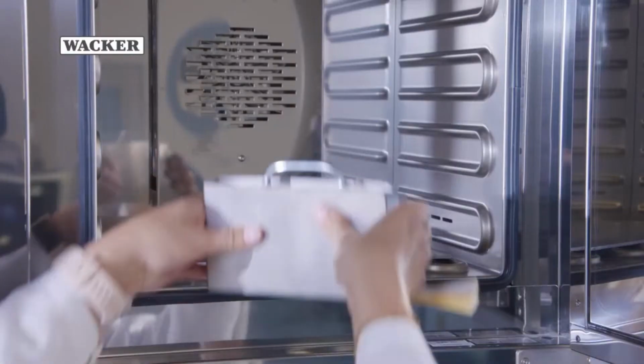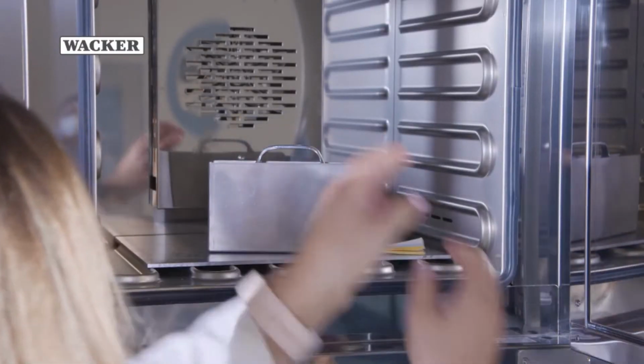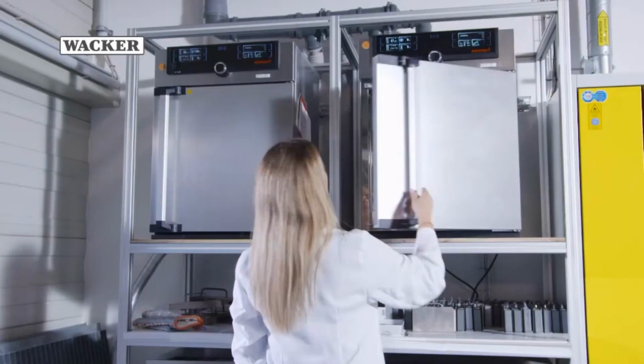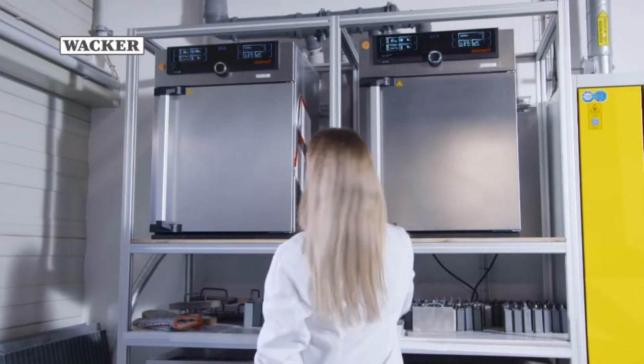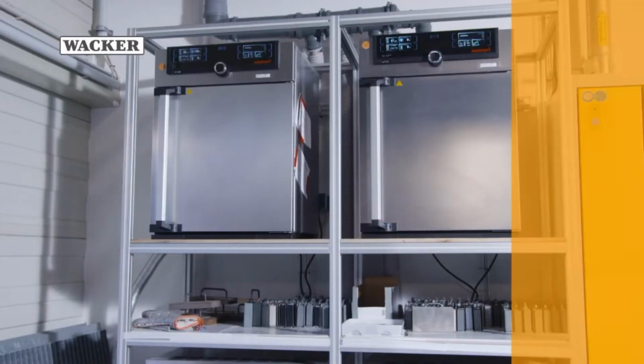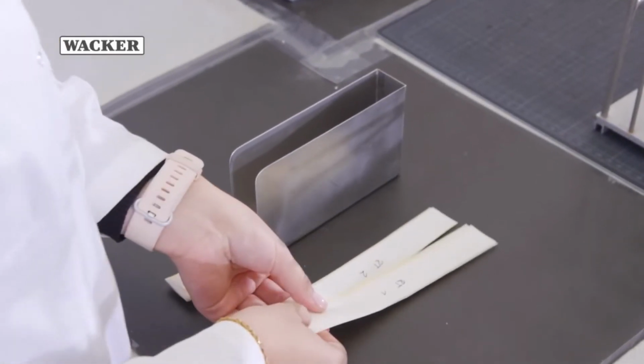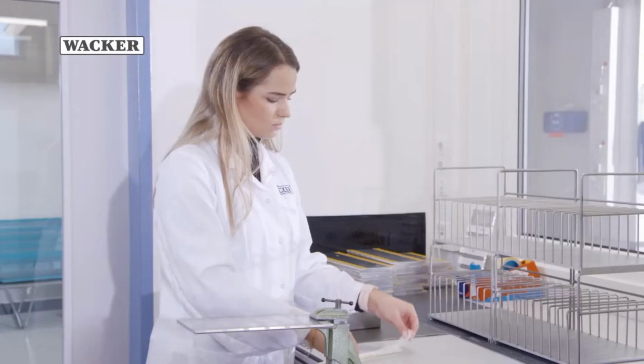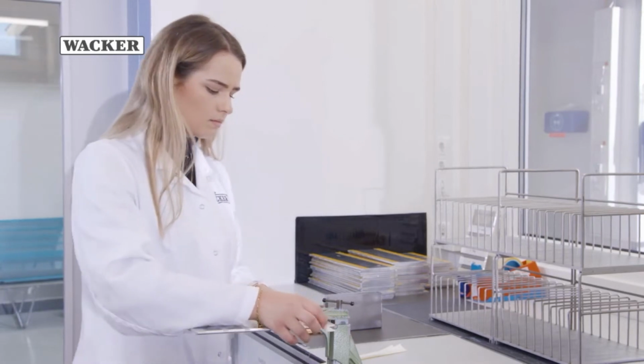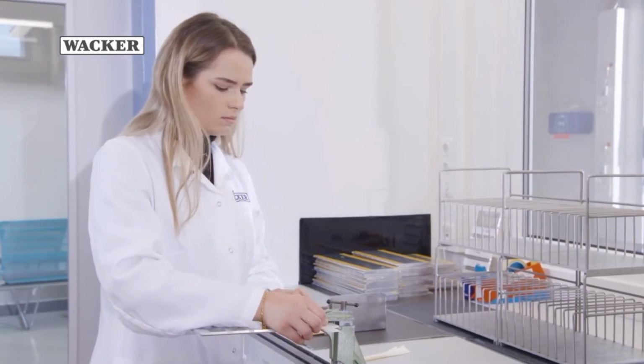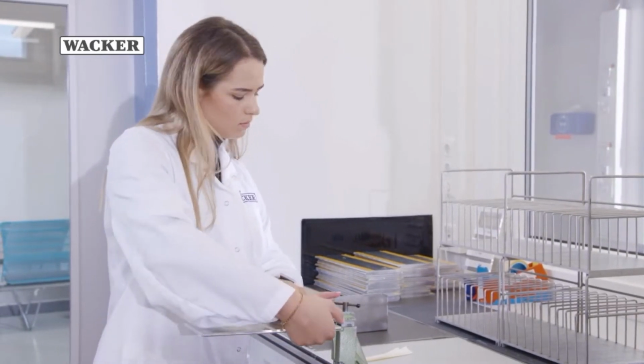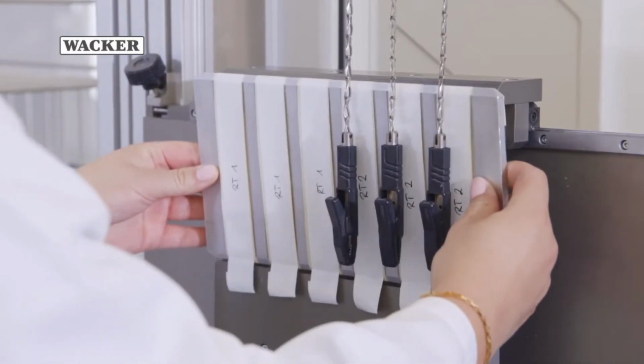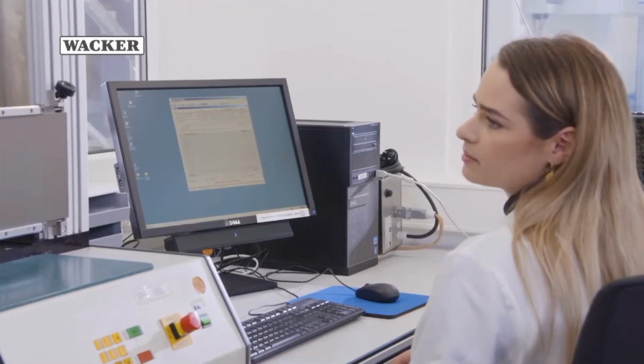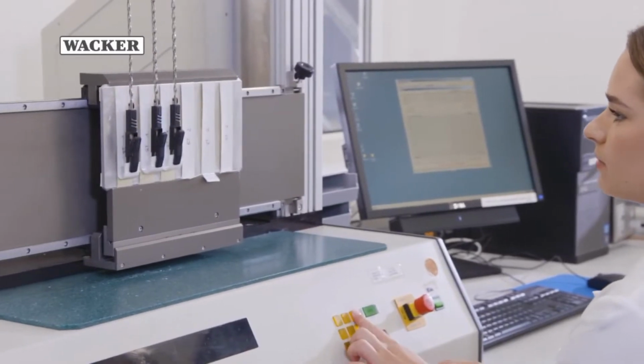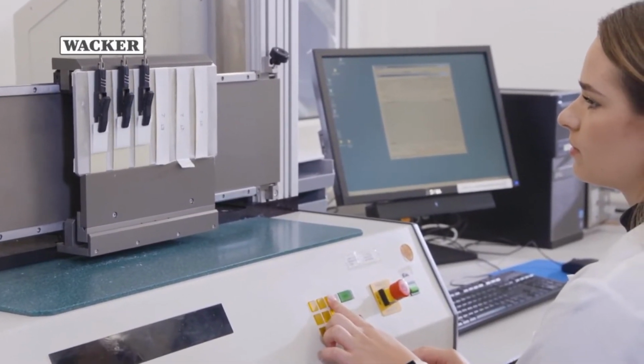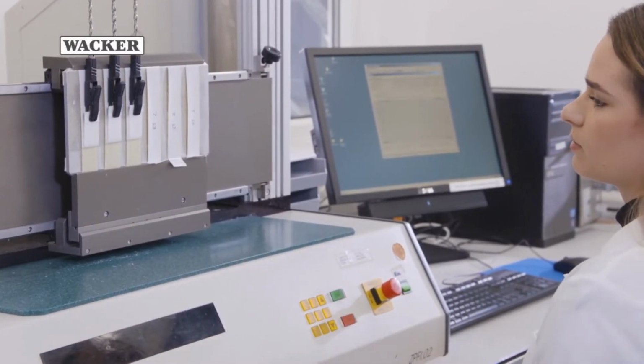Alternatively, prolonged storage periods and, for accelerated storage assessment, elevated temperatures of 40 or 70 degrees Celsius in a drying oven can be used. This storage ensures good contact between the release liner and the self-adhesive material. The prepared test strips can now be tested by 2 methods. Slow peeling determines the force required to peel the release liner off the adhesive-coated face material. This simulates the peeling off of labels by hand.